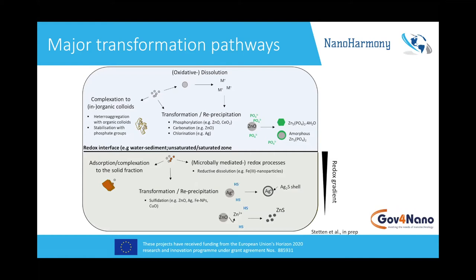The transformation pathways we discussed in terms of chemical transformation of core, shell, or surfaces. Dissolution and aggregation are also other pathways but they are not considered in the guidance document. We want to look into interactions with phosphate, carbonate, sulfate, and probably also chloride, because they tend to form poorly soluble metal compounds in the aquatic environment and have the potential to reform new nanomaterials.